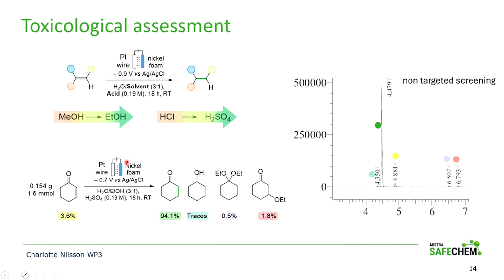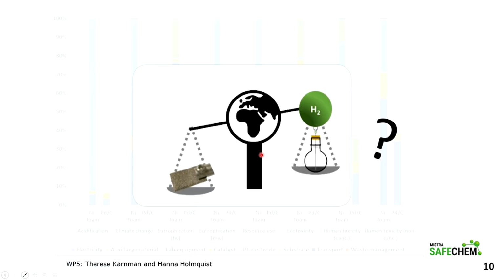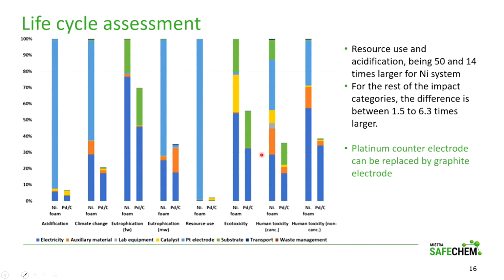We also did a non-targeted screening for this specific reaction and looked at what type of byproducts are formed after the hydrogenation reaction, and none of them showed any significant toxicity. So that was good. But is it really better, this system, than the palladium in terms of toxicology and life cycle assessment? So that's what we did in collaboration also with the other work packages. And what we looked into was the electricity use.